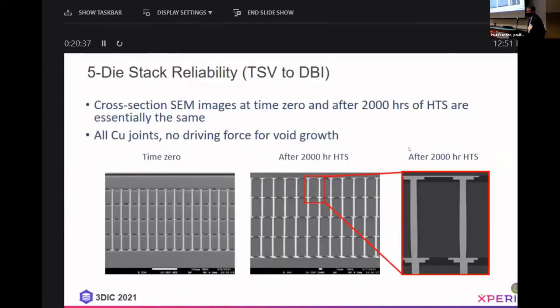This is a cross section of our 5-layer stack with TSVs and TSV to DBI bonding. And on the left, we have the time 0 picture of the stack, and then on the right, after 2,000 hours, you can see there's no degradation in the parts, no void formation, and basically with copper to copper joints, there's no driving force for void growth.